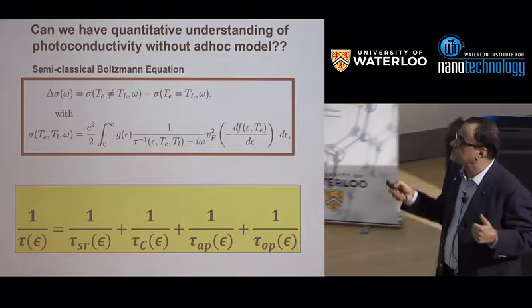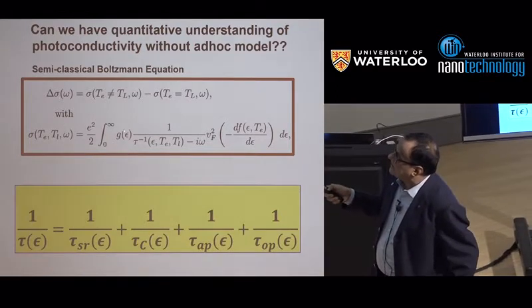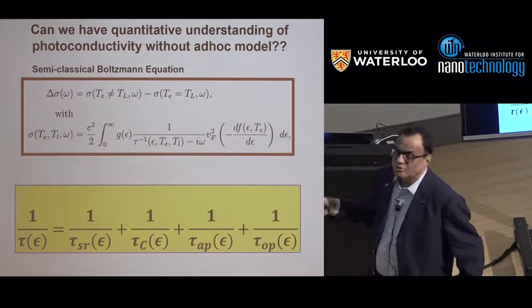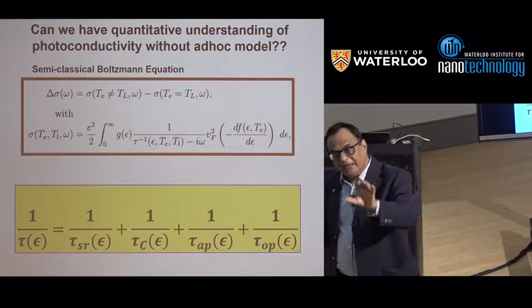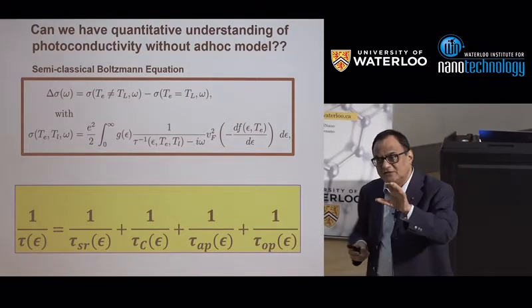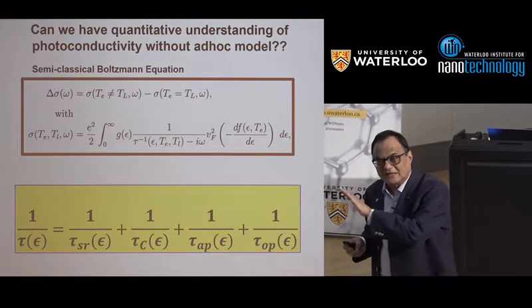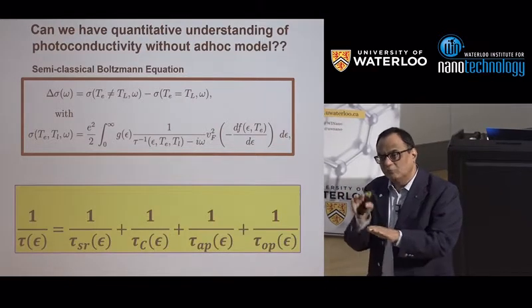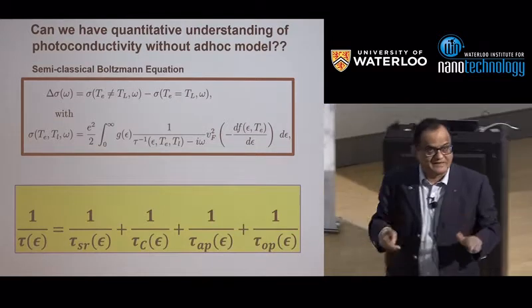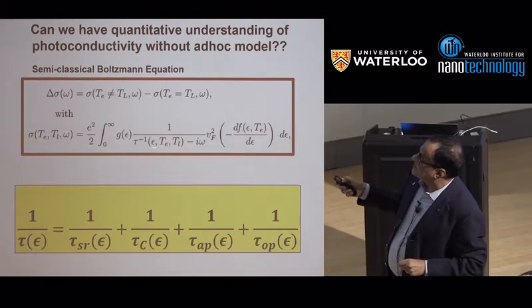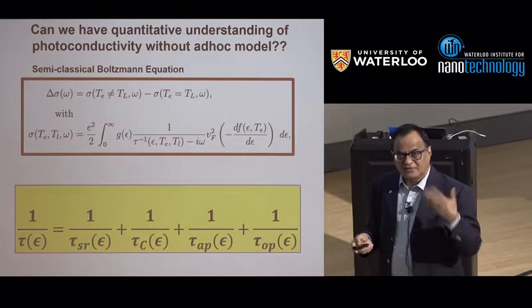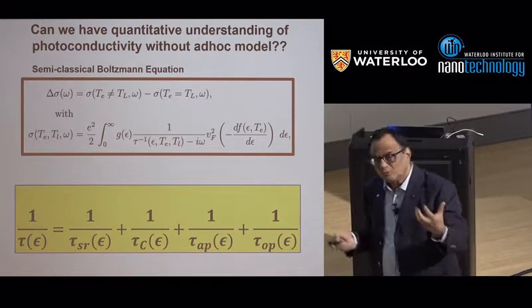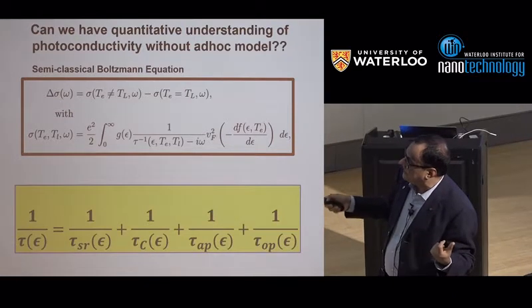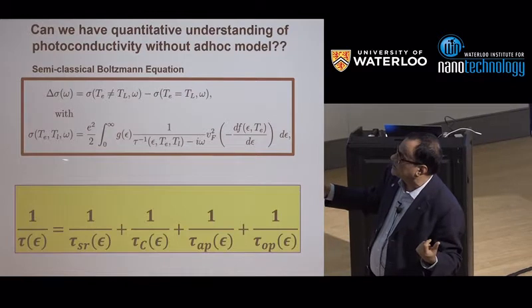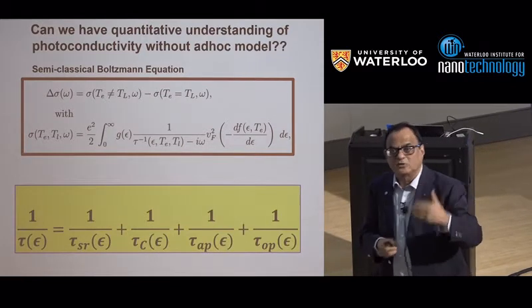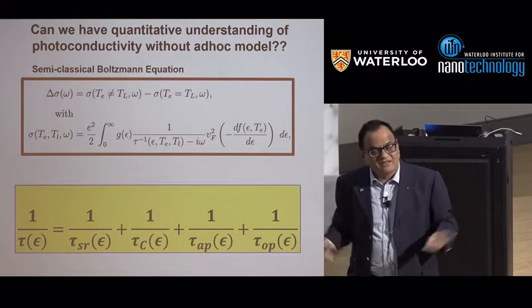But the $1 million question, which nobody had tried, is this: everyone takes tau energy independent, you pull it out and you get the simple Drude form. So we were paying for our inefficiency or laziness to do the full understanding and take a simple assumption that momentum relaxation time is energy independent. But this is not the case, and various processes you have to consider for this. If you understand that microscopically, then you can get the total effective rate, do the energy integration, calculate the conductivity at different electronic temperatures and see if it can explain your experiments.